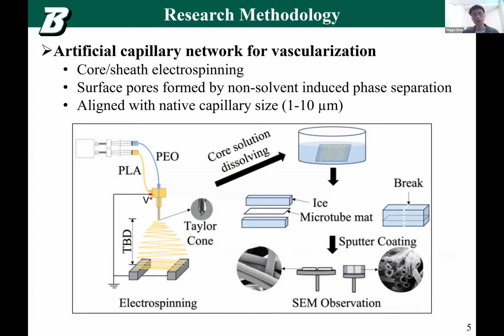The high voltage helps the solution at the needle tip break the surface tension of the polymer, meaning the electric force will exceed the surface tension of the polymer. When the electric force exceeds the surface tension, there will be a jet coming out of the needle tip. When the jet is coming out and the electric force is still in effect, the jet will accelerate and form a fiber structure before it goes to the bottom collector. The collector has to be conductive and grounded as well to be able to collect the structure.